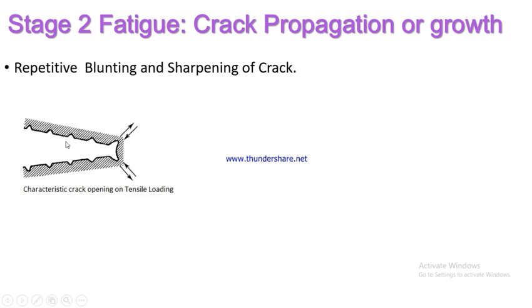Now let's go to stage 2 fatigue, which has to do with crack propagation and crack growth. Like we said before, in the first stage those cracks are initiated. For those cracks to propagate or grow, there are other mechanisms associated with them. The first part is what we call crack opening, which has to do with repeated blunting and sharpening of the cracks, which makes the cracks propagate and grow.